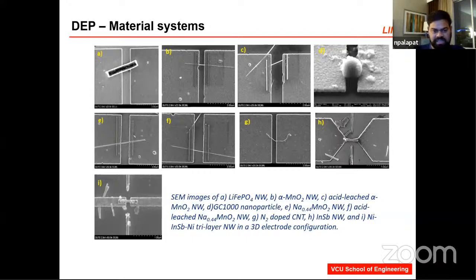And last but not the least, the last one, if you look carefully, you have additional pads on top of the pad, and the nanowire is sitting on top of the pad. So it's a three-dimensional configuration that we were able to achieve. And the nanowire itself is also a tri-layer nanowire: indium antimonide, nickel, and then indium antimonide. So these are several nanomaterial systems that I worked on in my graduate study. I deposited them, worked with all these parameters, analyzed, then characterized them for different applications.